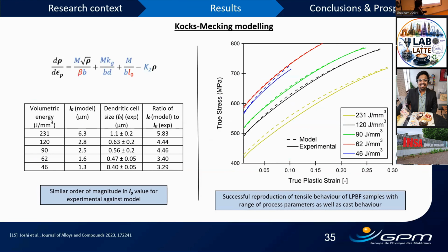So solving this, we can reproduce the tensile curves, and also we can see the modeled values for L0. Of course, the model overshoots a bit compared to experiments. The ratio is from 3.3 to 5.8 for different volumetric energy densities. But in general, we can see that it acquires a similar order of magnitude. So using this analysis, what we proposed here, and this work has been recently published as well.